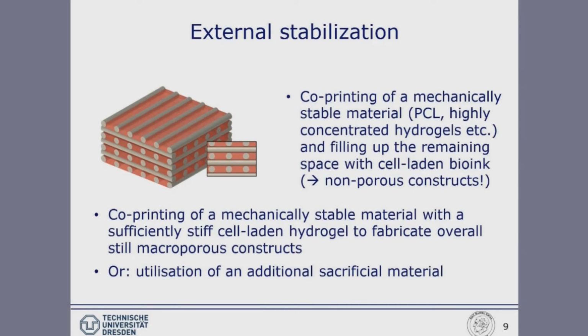With these two examples for the technical solution, I already want to go forward to the approach we want to call external stabilization, which is maybe the most common one if macroscopic bioprinted scaffolds are fabricated. What is done here is that the soft cell-laden hydrogel is combined with a much stiffer supportive material like a thermoplastic polymer. In most studies published in this field up to now, polycaprolactone is used due to the low melting point of this polymer. But more and more, other materials are also successfully tested in this approach.